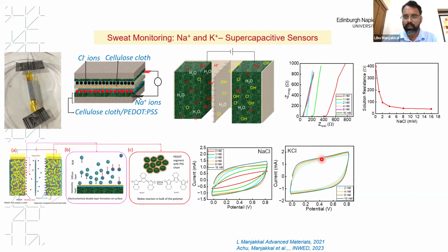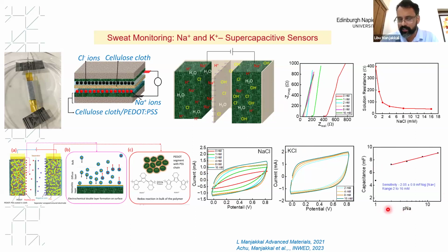And when we made a systematic analysis of the variation of the concentration, as you can see from here, the sensitivity of the sensor, for example the sodium chloride sensor, is 2.5 to almost 2 millifarad per variation in the sodium. As you know, in a normal capacitive sensor, the variation is in the nanofarad or microfarad range. But with the supercapacitive sensor, we got a very high value. That means the interference will be very low, and it's in the millifarad range. So these are some of the ion monitoring sensors we developed.